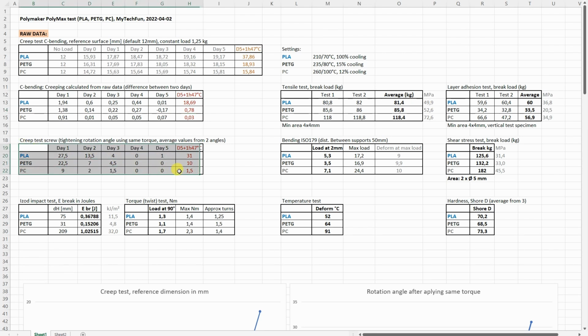The screw creep test is already in the differences. So here the 0 means no creeping. And here we can see some additional information. These are in megapascals because I prefer this kind of values because it's easier for understanding for non-mechanical engineers. If I tell you that 4x4 millimeters broke on, I don't know, 100 kilograms, it's easier to imagine the load compared to these megapascals. But anyway, I left here these data because these are given in specification tables. Here we have the same with the Izod impact test.